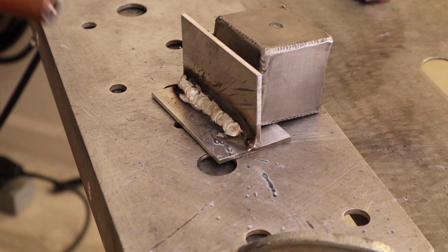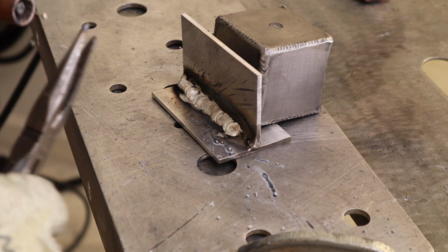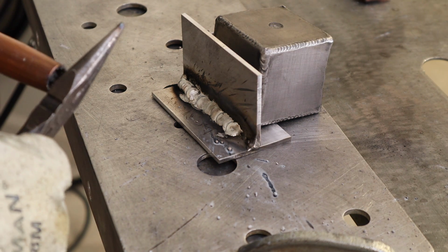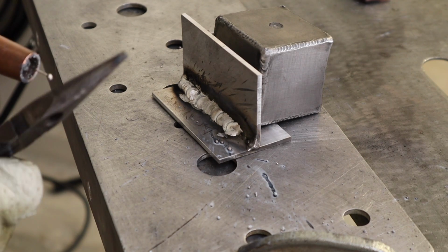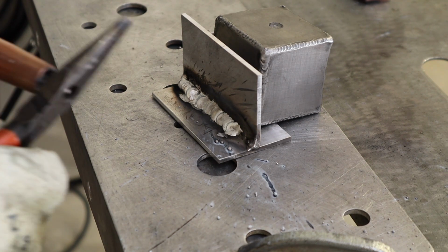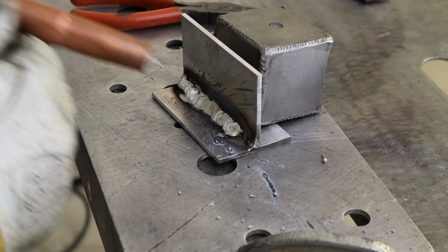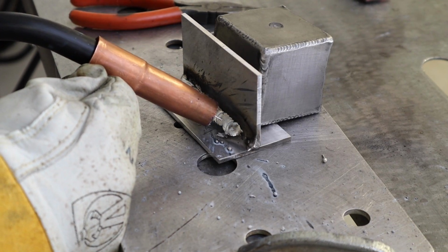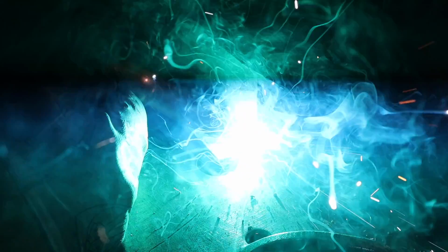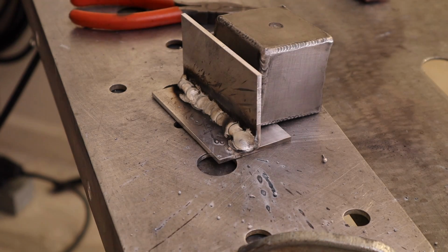You heard that little whistle sound and I got burned back on the tip. And that's going to happen several times as I proceed with these welds from here on out. It gives a little whistle and it burns back right to the contact tip. Now, I never did weld the aluminum to the tip, but it would burn back right to the tip and it would stop feeding because I've got my wire feed tension set very lightly so I don't end up with a bird nest. But it does lay down a pretty nice bead.